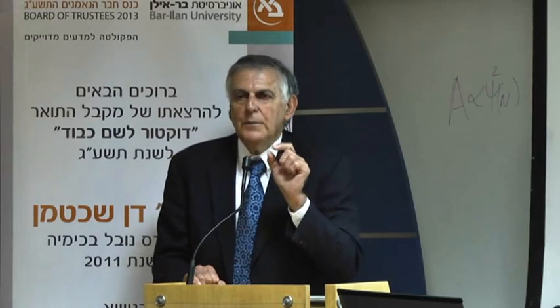But with X-rays, you could not have discovered quasi-periodic materials because they were very small. In order to obtain, at least in those days, 30 years ago, X-ray diffraction from a single quasi-periodic crystal, you need the crystal to be of some size, something that you can feel between your fingers, like a grain of sand from the beach, a portion of a millimeter. We did not have that. It took us 3 years to grow such a crystal, and then we had X-ray diffraction.